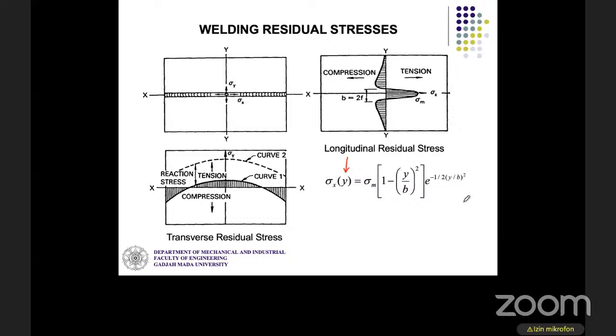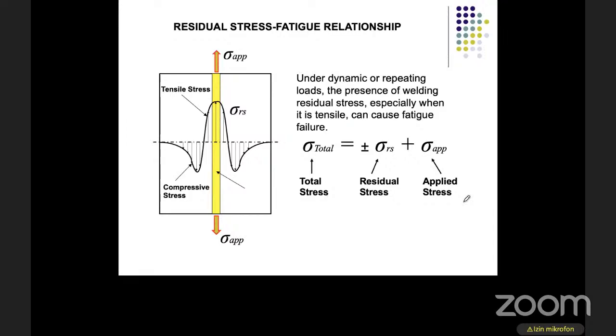And actually, the residual stress can affect the fatigue behavior of the weld. This is because by using the superposition approach, the total stress when applied stress works in the structure equals residual stress plus applied stress. So it means that when the residual stress is tensile, it magnifies the total stress. But if the residual stress is compressive, it reduces the total stress. So in this case, tensile residual stress is more dangerous compared to compressive residual stress.